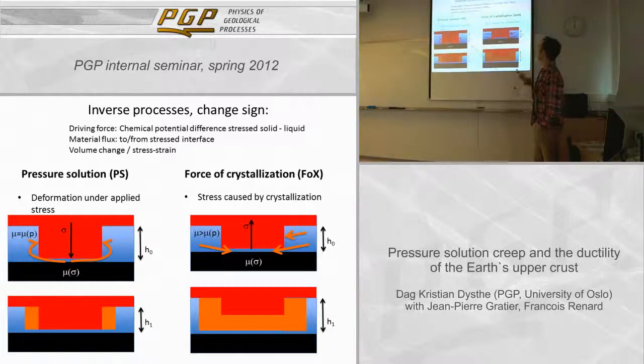Okay, so now a little bit more detail about the process itself. The driving force for pressure solution is that you have a stress, and that there is a chemical potential difference between this region where there is a large normal stress and other regions where there is lower normal stress. So there is a chemical potential difference between here and there, which drives mass transfer from here to there.